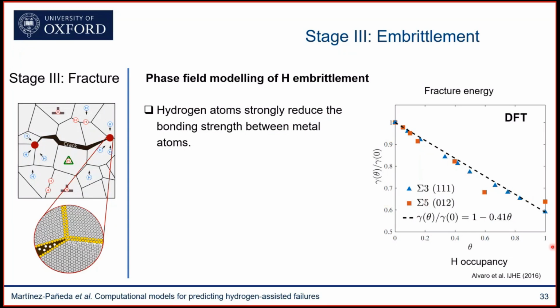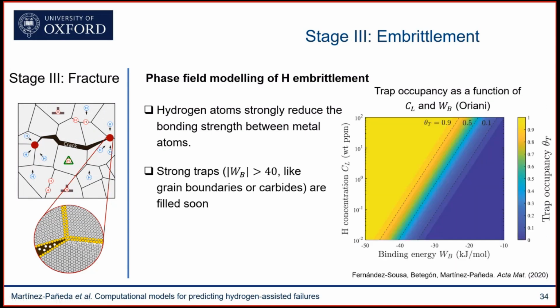But of course, the key question here is, okay, where are we in this x-axis, right? Because if somehow the hydrogen occupancy in grain boundary is over here, then this is a secondary effect, and there must be other mechanisms playing a role. And the answer to that comes from the thermodynamics of trapping. And we can do experiments in our lab. We can measure binding energies. We can see how energetically favorable it is for the hydrogen to go to certain microstructural defects. And we can use Oriani's equilibrium to relate those binding energies with the hydrogen concentration and the trap occupancy.